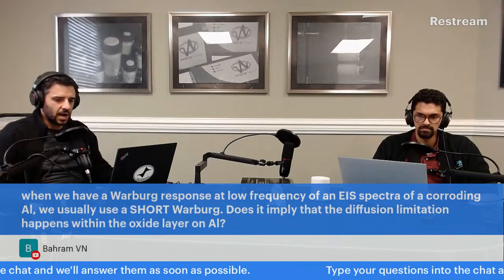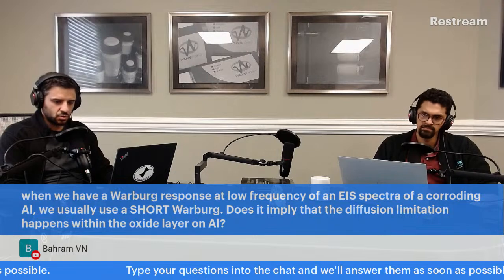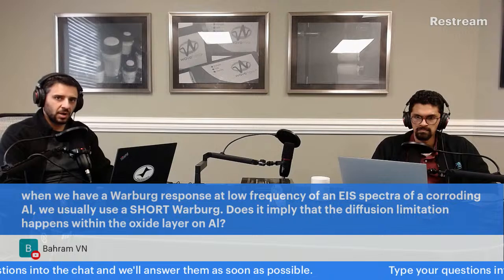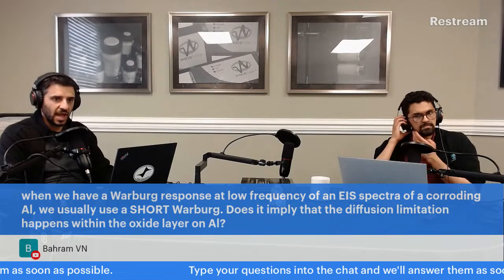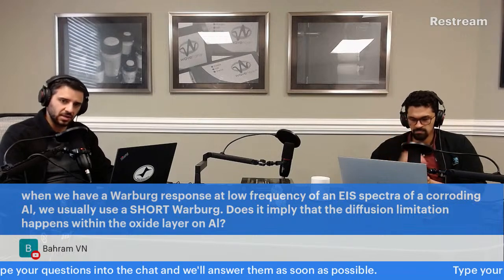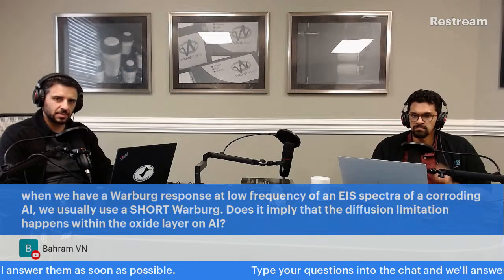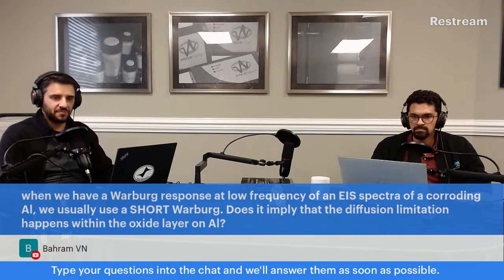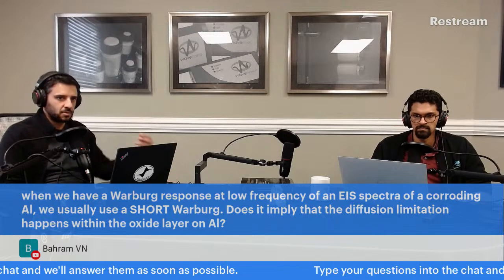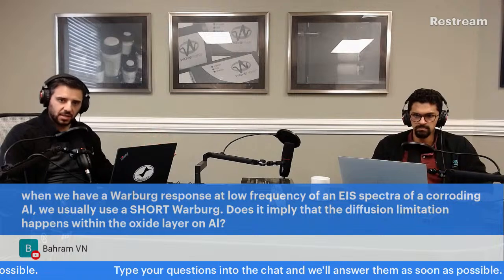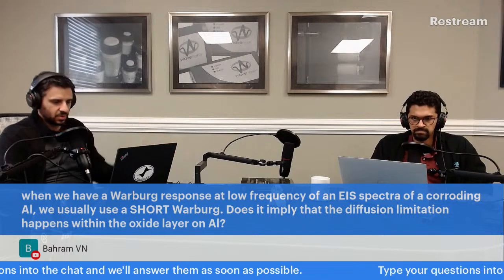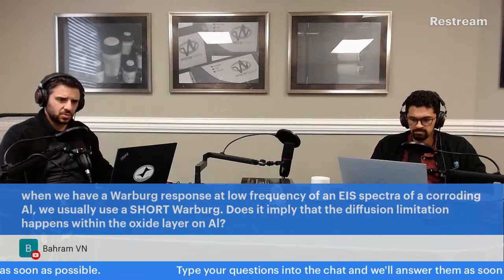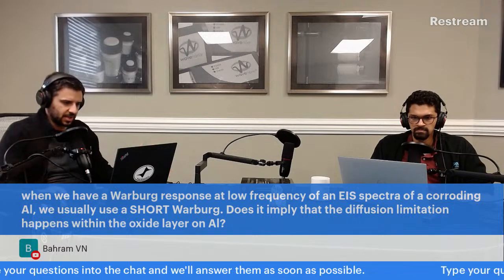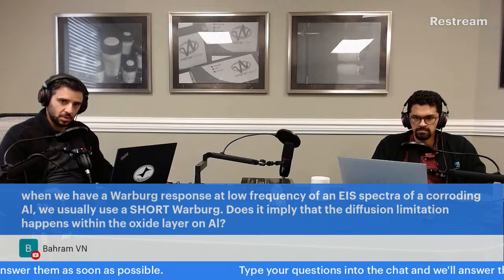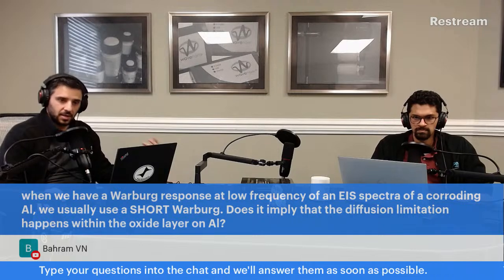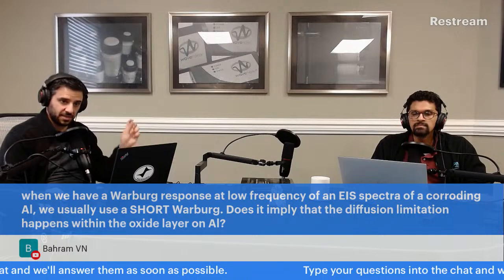So I think that whether it is within the oxide layer or not is probably a little difficult to determine. But you might be able to try to independently verify, for instance, by taking the Warburg constant you get from the Warburg short, or actually the other constant, to be honest. We call it B in our software. It might be called something different in other circuit fitting programs. A Warburg short has two circuit fitting parameters you get out of it: one is the Warburg constant, and the other we call B. It is equivalent to the square root of D over the diffusion layer thickness, or something like that. Effectively, that B is proportionate to the diffusion layer thickness, so you can in some way quantify the thickness of the Warburg short.